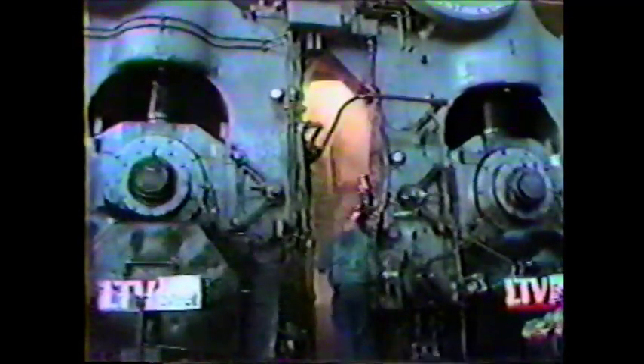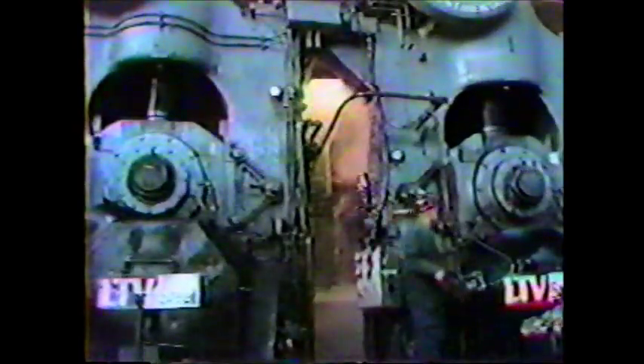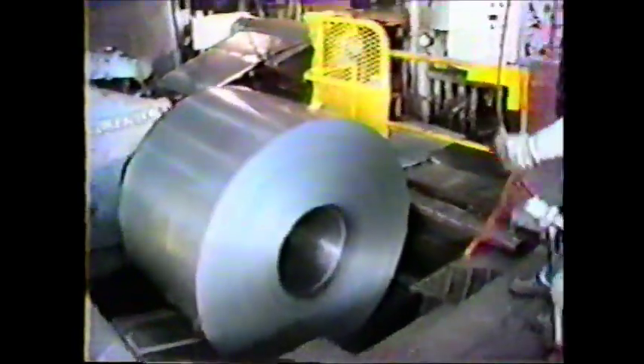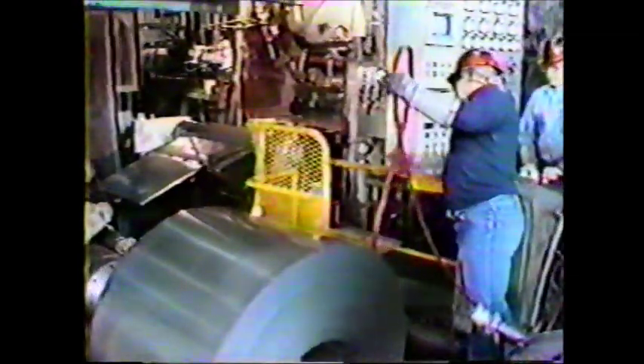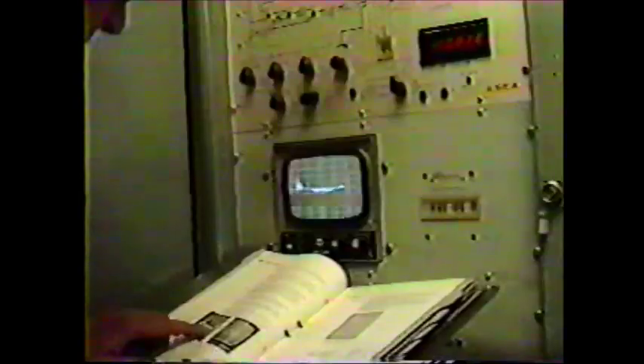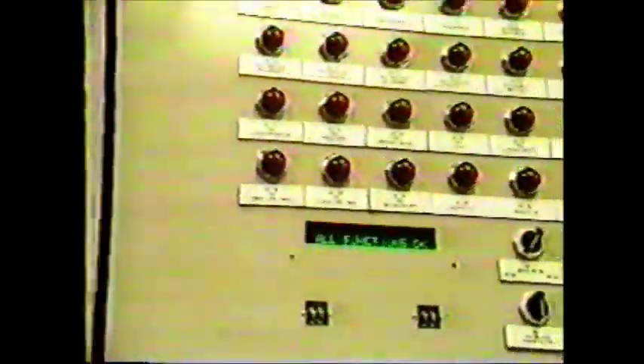The 4-stand tandem mill cold reduces pickled coils to near final gauge, controlled by a quick response hydraulic system. Integrated process controls have maximized strip cleanliness by improving the rolling solution tested meticulously in the rolling and finishing lab. This video screen at the roller station displays any variation in strip shape through transducers mounted in a segmented roll, measuring tension at 2-inch intervals. Warren's stressometer flatness control system by ASEA Metallurgy is the first installed in a United States steel facility.